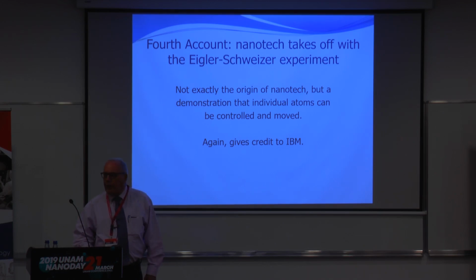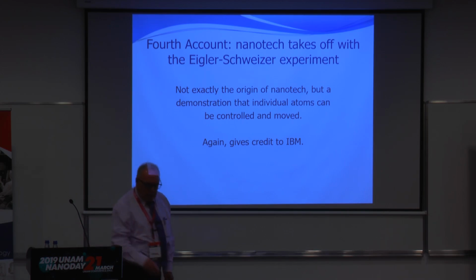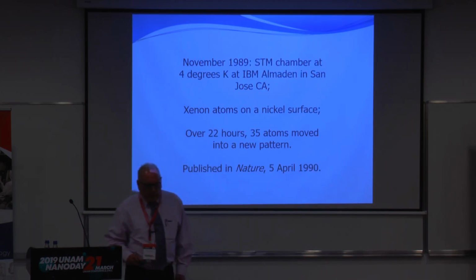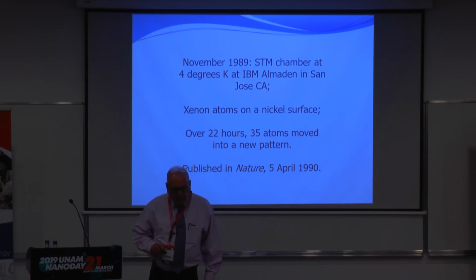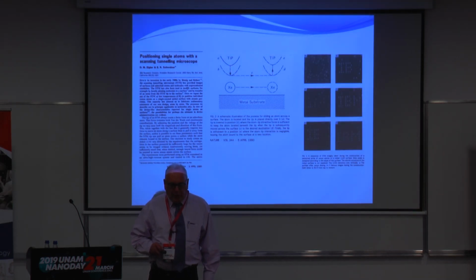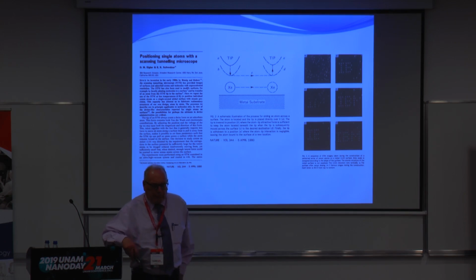And then over a period of 22 hours, they used the tip of the scanning tunneling microscope to pick up 35 atoms one by one and to spell something out. So that was published in Nature in April of 1990. So the process goes like this. They're showing you there in that central image that the tip is coming down very, very close to a xenon atom, such that the atom bonds to the tip, and then the tip is moved horizontally, thereby dragging the atom into a particular place. And this is done 35 times.